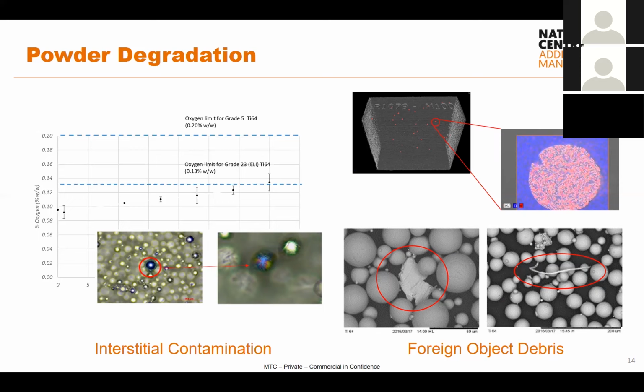0.13% weight oxygen. Now what we can see is as we recycle and reuse the material, the oxygen content is increasing to the point where eventually, sorry I've covered the numbers up, but it's 5, 10, 15, 20, 30, 35, roughly 35 builds, it eventually transitioned past that spec line. So this material, if we needed a part that was ELI, this material is no longer suitable. We'd have to scrap this material at this stage. Now what's important is that if this is a linear trend, as it appears to be, and this would happen whatever the starting condition, clearly if we bought material that was at 0.1, it's still ELI powder, but clearly if it picks oxygen up at the same rate, we're not going to get very many builds at all before it transitions.